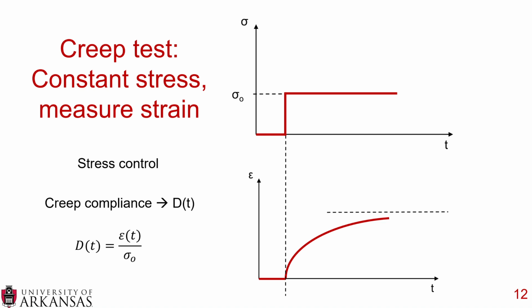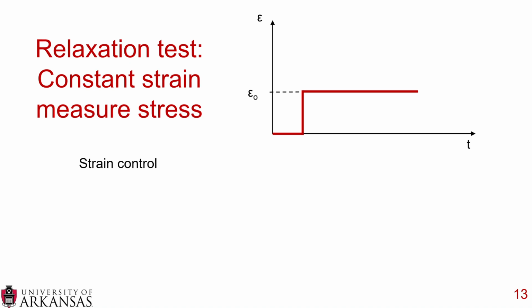So you apply some sort of initial stress, and at the time of application your strain starts increasing, and you can see it's asymptotical. It never gets to a maximum limit, but approaches a maximum value. So this is the creep test: constant stress, measure strain. The relaxation test, on the other hand, is a constant strain, and you measure the stress.